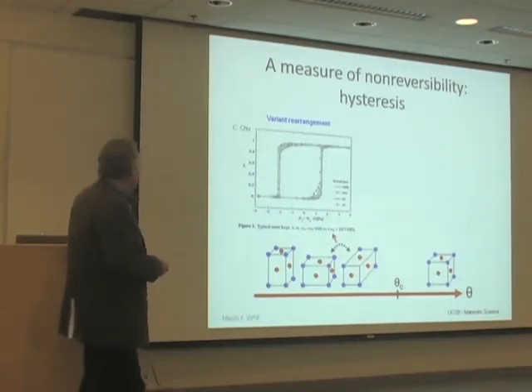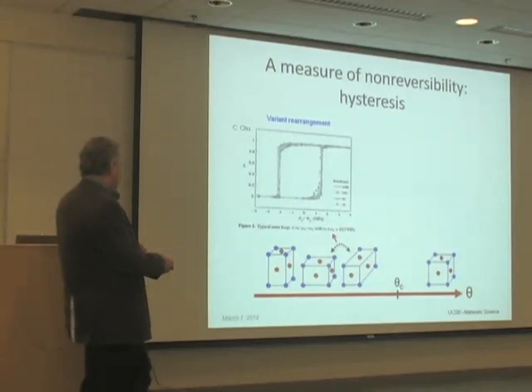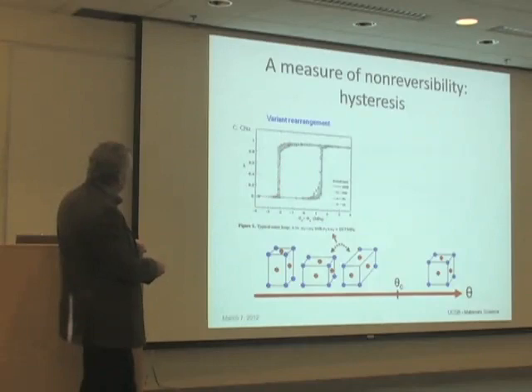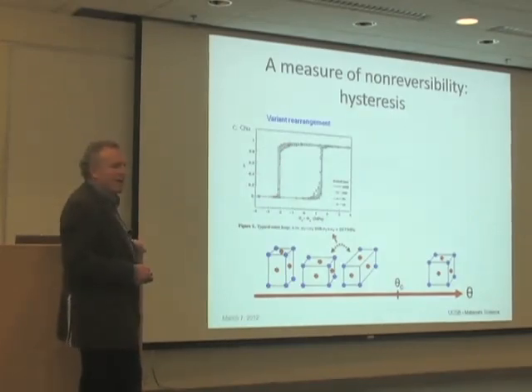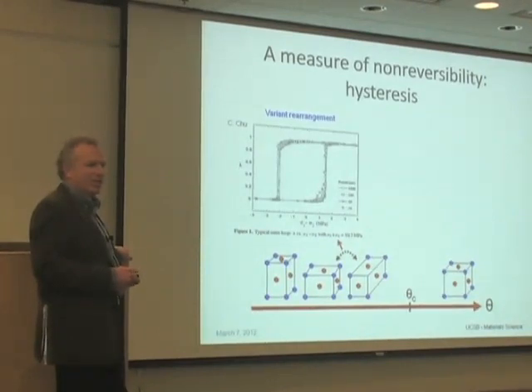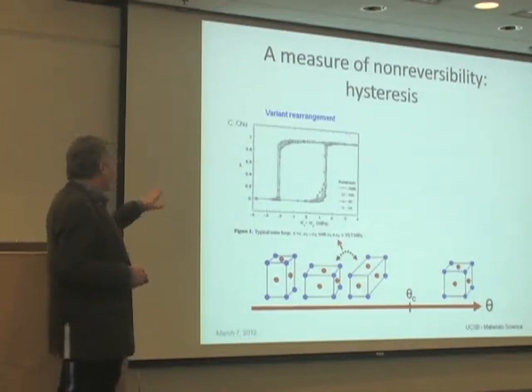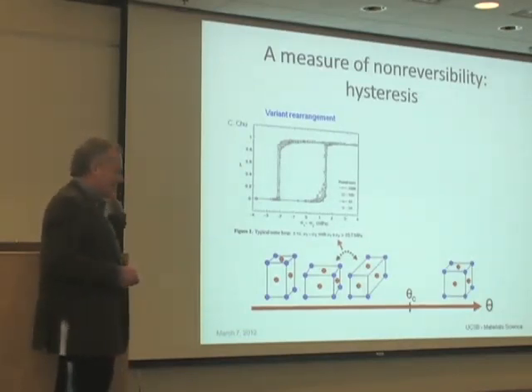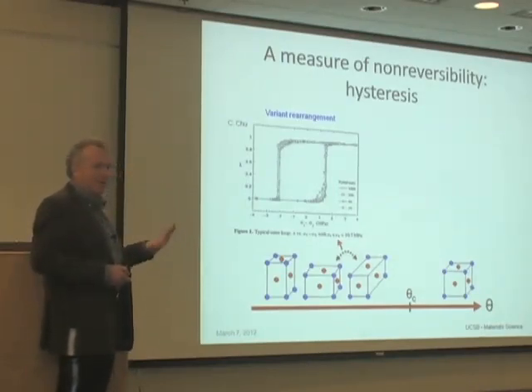And so you can see that it transforms in one direction at some stress and in the reverse direction at a different stress. But the main reason I put this up here is that in this experiment, the rate of loading was varied by two orders of magnitude. But you can see that the hysteresis is about the same. And that's so-called rate-independent hysteresis. And that's the typical kind of hysteresis in phase-transforming materials. There is a small rate component, but the main part is rate-independent and does not shrink to zero no matter how slowly you do the loading or you do the changes of temperature.